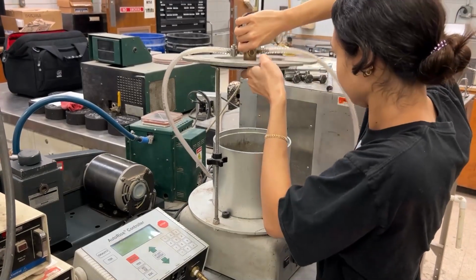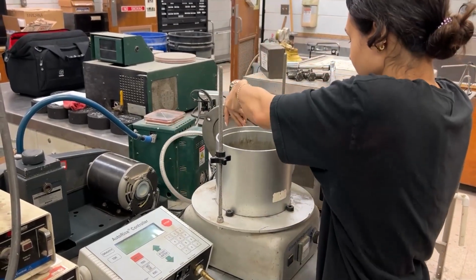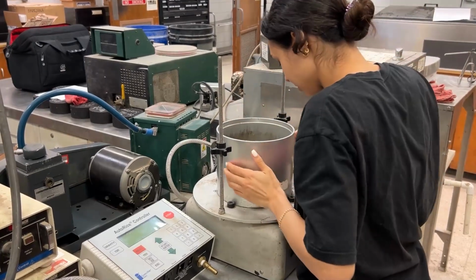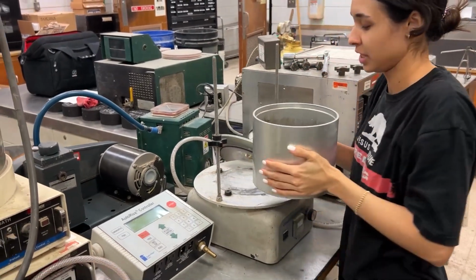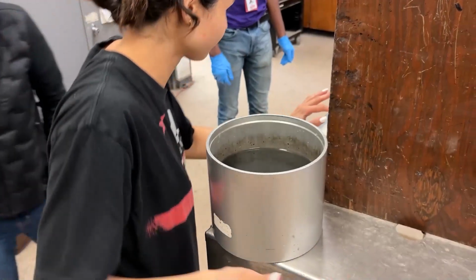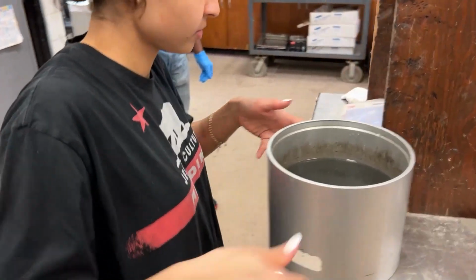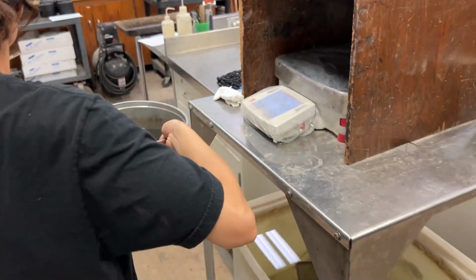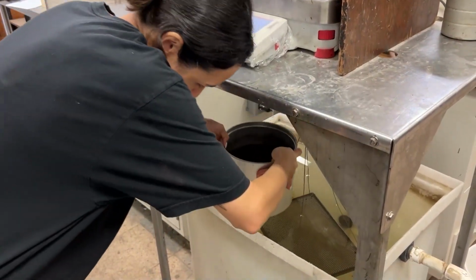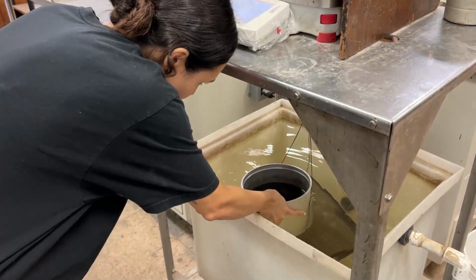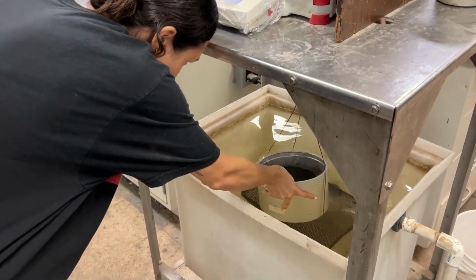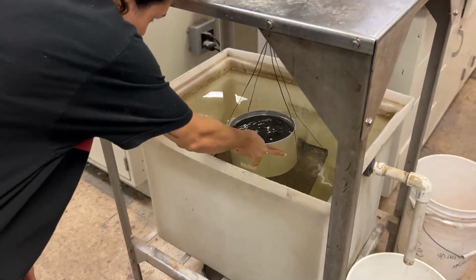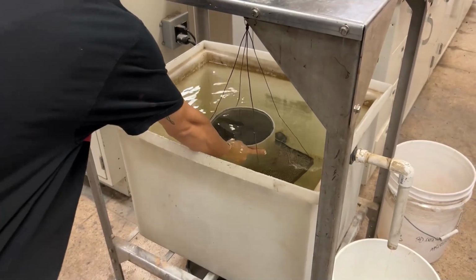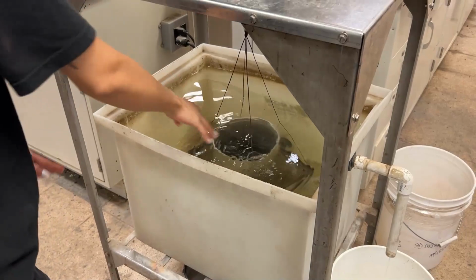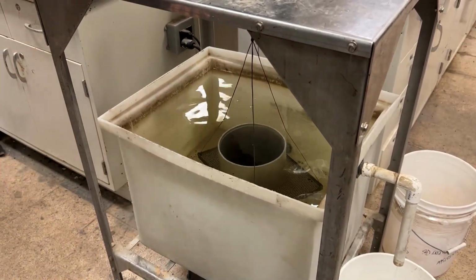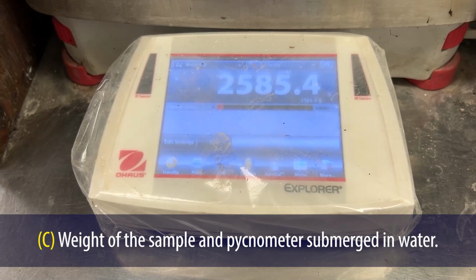Next, release the pycnometer from the shaker table. Having vacuumed and vibrated the sample for 15 minutes, we can be assured there are no air voids in the asphalt sample. At this time, make sure our balance is zeroed out, the water temperature is at 25 plus or minus 1 degree Celsius, and the water is up to the overflow outlet. Place the pycnometer onto the suspension apparatus and slowly immerse it into the water bath for 10 plus or minus 1 minute. Determine and record the mass as C.